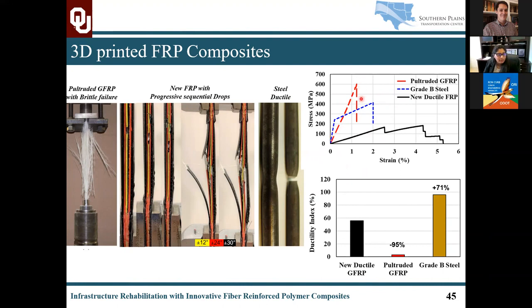Compared to this traditional GFRP, we've seen that using 3D printing with different orientations, here I'm showing a sequence with 12 degrees fiber, 24 degrees fiber, and 30 degrees fiber, all stacked up to form one FRP system. So this new FRP with progressive sequential drops, this particular composite was loaded under tension. And you see that there is a progressive failure. Not all layers fail at once, resulting in this brittle explosive failure, but there is a sequential failure where every layer fails one after the other in a progressive sequential pattern. This in turn resulted in a more ductile, pseudo-ductile behavior that can see much more improvements in the future in order to get a more ductile, non-linear kind of behavior.